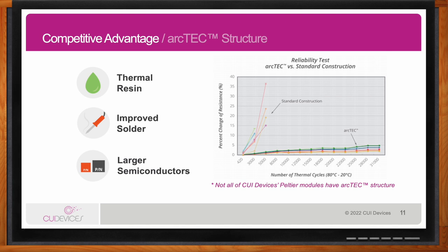The major advantage of the arcTEC structure is highlighted in the graph on the right-hand side of this slide. And what this graph shows is the number of thermal cycles, as I mentioned earlier, starting temp down to target temp, over time, and the percentage change in thermal resistance. For purposes of these slides, we'll be using a thermal cycle of 60 degrees, so starting temp of 80 degrees and bringing it down to 20 degrees, which is also known as a delta T of 60 degrees C, which I'll talk more about when we look at actual specifications.